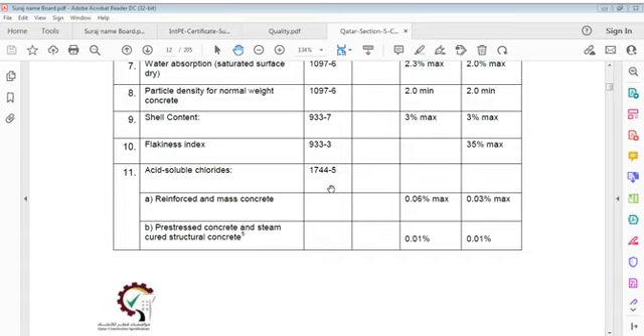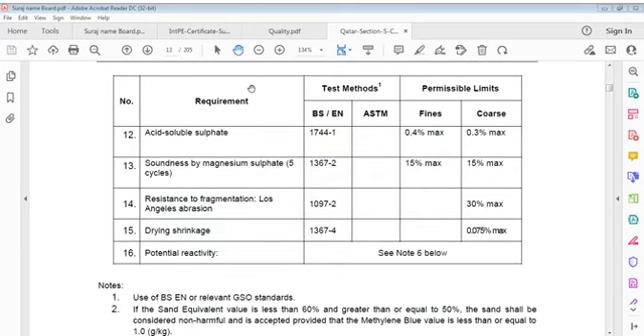Acid soluble chloride, 1744-5, in which case for reinforced and mass concrete, fines 0.06% maximum acid soluble chlorides and for coarse 0.03% maximum. For pre-stressed concrete and steam cured structural concrete, 0.01% acid soluble chlorides for fines and coarse. Then acid soluble sulfate, test method is BS 1744-1. Fines are 0.4% maximum acid soluble sulfates and coarse is 0.3% maximum.